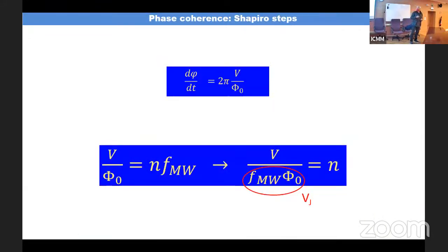So if we go now to time evolution of the phase and Shapiro steps, under an applied voltage, there is this time evolution of the phase. This is the second Josephson equation. And basically the voltage over phi naught is a frequency, right? And when this frequency is a multiple of the microwave frequency under radiation of the sample with microwaves, there is phase locking. There is strong resonant absorption, and the sample goes to the normal state, and you see an increase of the resistance. And changing the voltage produces these resonance conditions in which the sample goes to normal and produces these steps in the resistance, which are the Shapiro steps, right?